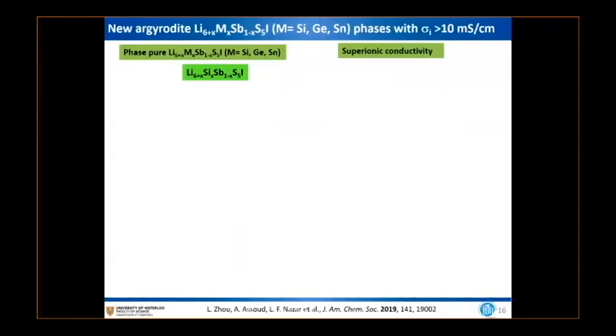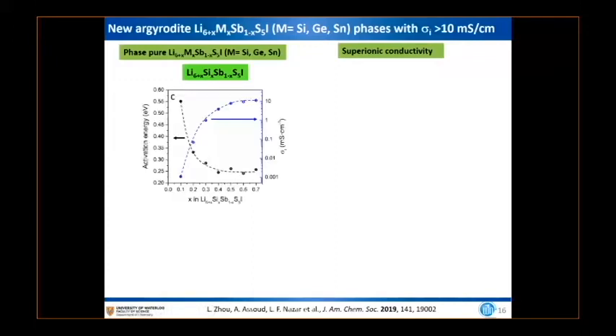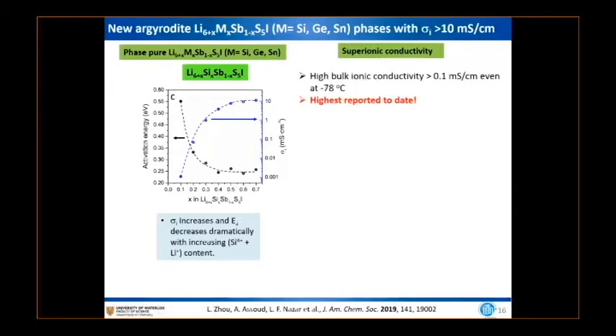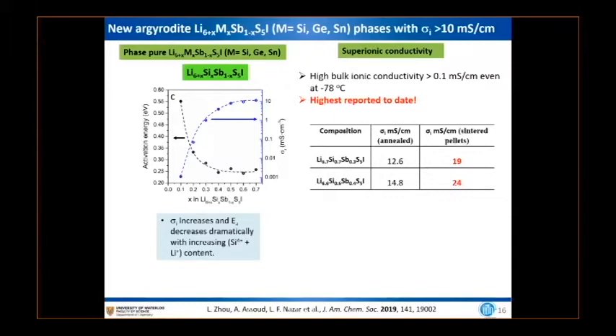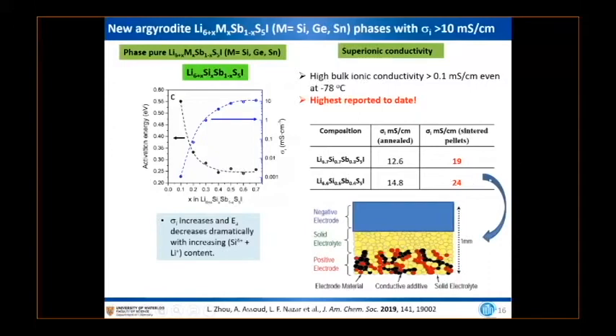So the first thing my group developed was a conductor with not just above 1 millisiemens, but above 10 millisiemens per centimeter conductivity. And this is through chemical design of a new class of materials. And I show you here the conductivity as we tweak the composition, going from very low to above 10 millisiemens per centimeter. And even at minus 78 dry ice temperatures, the conductivity is at 0.1, which is not quite the benchmark, but it's still the highest reported to date. And when we press these pellets, we can get conductivities upwards of about 20 millisiemens per centimeter. So these materials we're using as separators in our cells, so we're using them for this yellow portion that I show here.